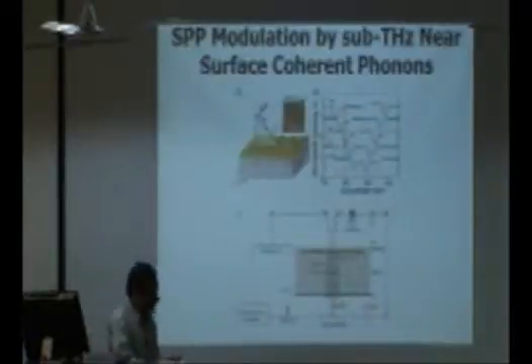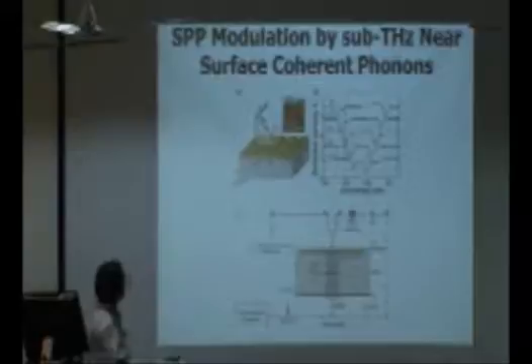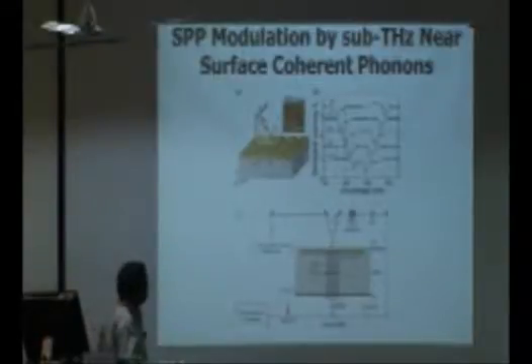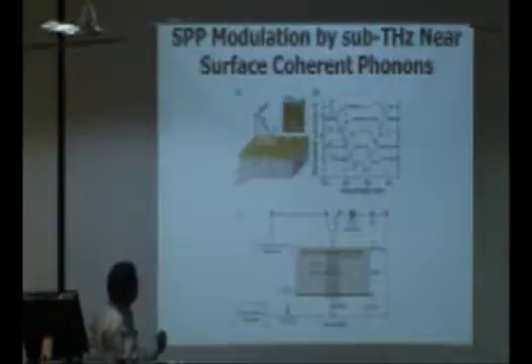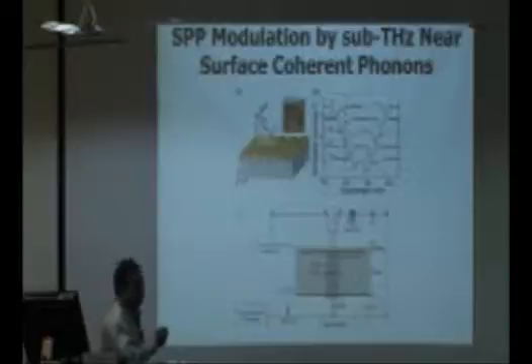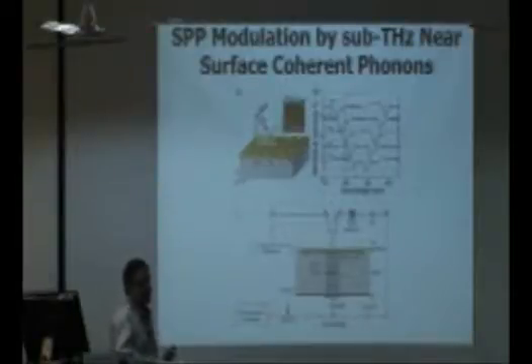So the more recent work is on surface plasmon modulation by acoustic phonons. The idea is that we have these periodic structures on the top, gold gratings, which will help in coupling light to the plasmon modes. So the plasmon modes are excited at this interface. Now, can we modulate these plasmon modes by external means?